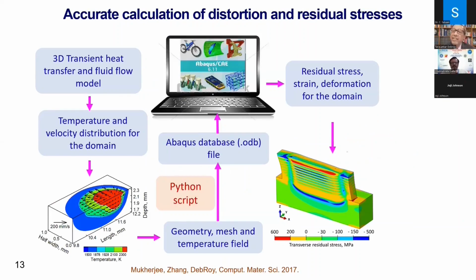The second thing is residual stress and distortion, which is a huge issue. I showed you a picture of a part getting delaminated from the base plate. So what we are doing here is to make the process more accurate. Commercial codes like Abaqus and ANSYS do not do accurate heat transfer and fluid flow calculation. They only do the heat conduction equation. And the heat conduction equation can be notoriously wrong because the primary mechanism of heat transfer within a fusion zone is convection. So if we ignore the primary mechanism of heat transfer, there are consequences.